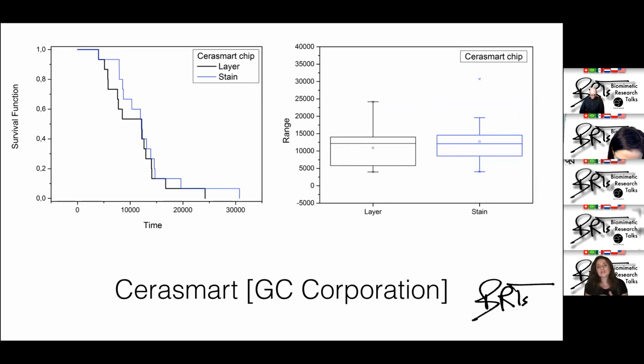So it didn't really matter if we applied the colorant between the layers. It allowed us to achieve a much better result in the clinic. It allows us to achieve this 3D color dimension and natural result, which will not cause the colorant to wear off fast after the restoration is delivered. And it doesn't influence the strength of our restoration.